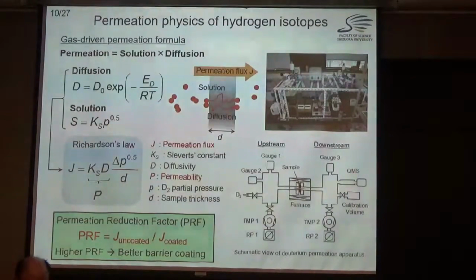So we constructed the deuterium gas permeation apparatus shown here. So here, just two vacuum chambers, and the sample is located here. Then one side is filled with deuterium. Then the permeated deuterium can be detected by a quadrupole mass spectrometer. Then we can compare the permeation flux with coating and without coating. So then we can calculate the permeation reduction factor. So the higher PRF means a better barrier coating. So we are aiming to get more than 1,000 or something like that.